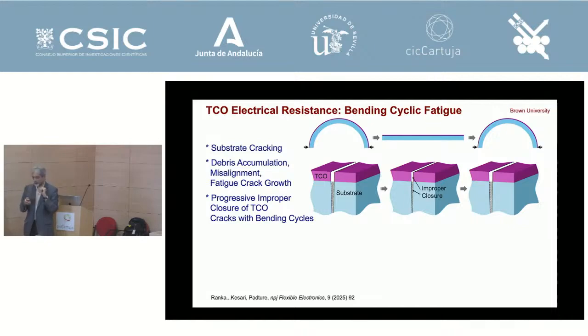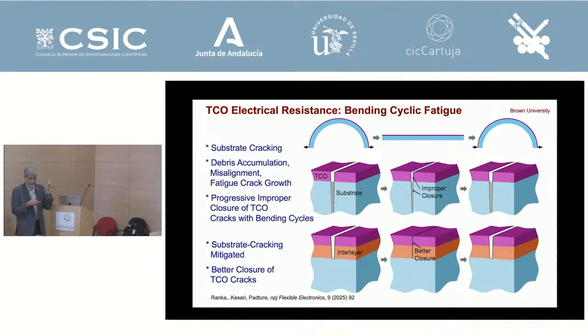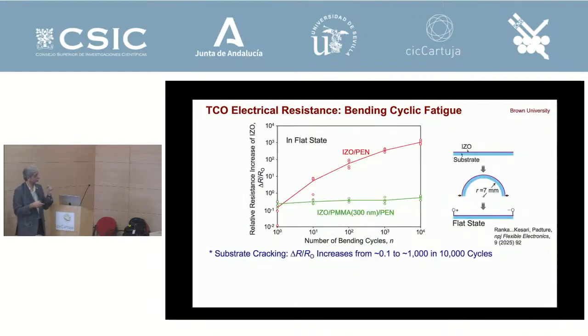The contact is improper. But if you prevent the substrate cracking, then you can actually have better connection between the ITO layers. And that's what we show here. So you get 4 orders of magnitude change here, but with the interlayer, where the substrate doesn't crack, the resistance really remains almost the same over 10,000 cycles because the substrate did not crack. So whenever you made it flat, the coating came in contact to pass electricity, right?